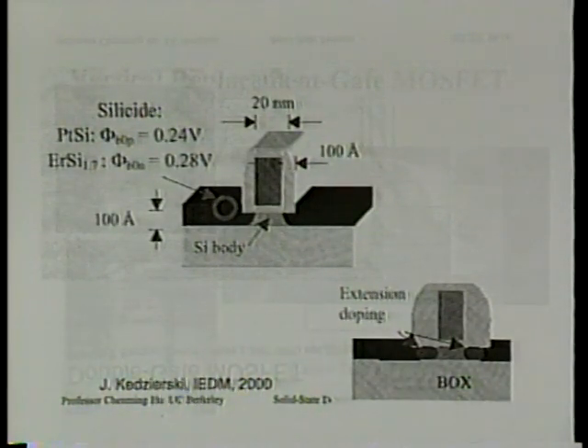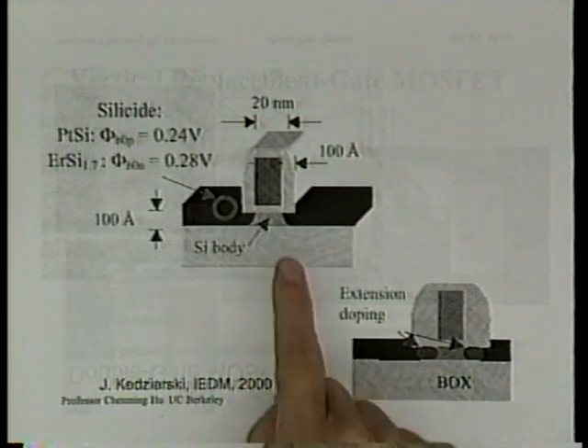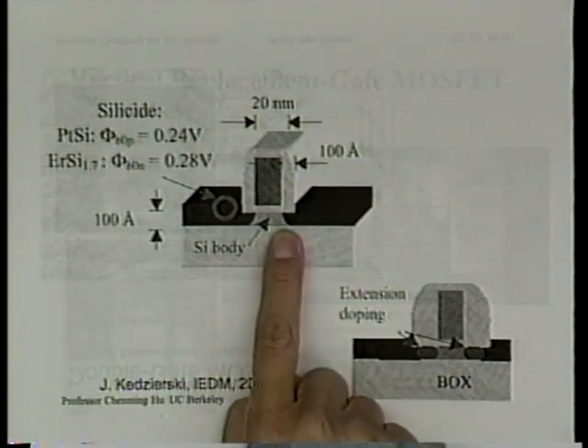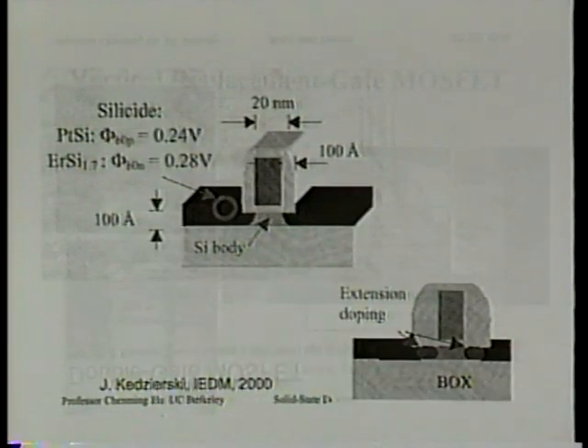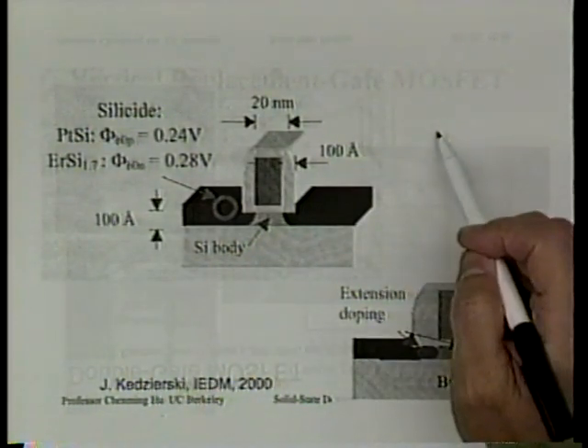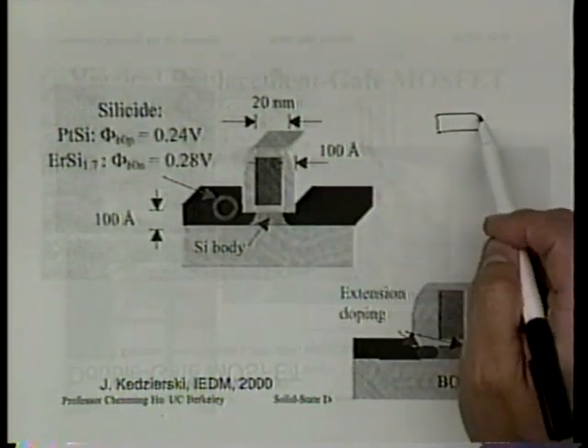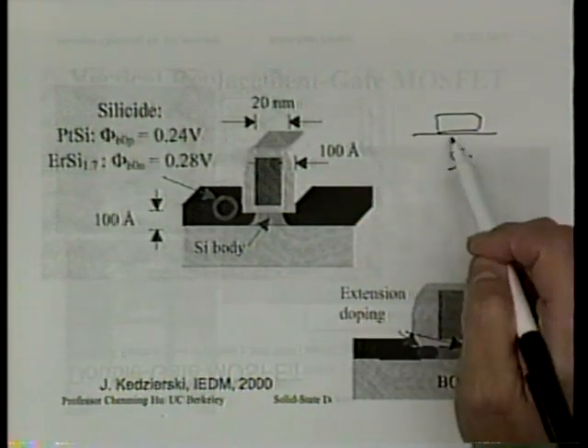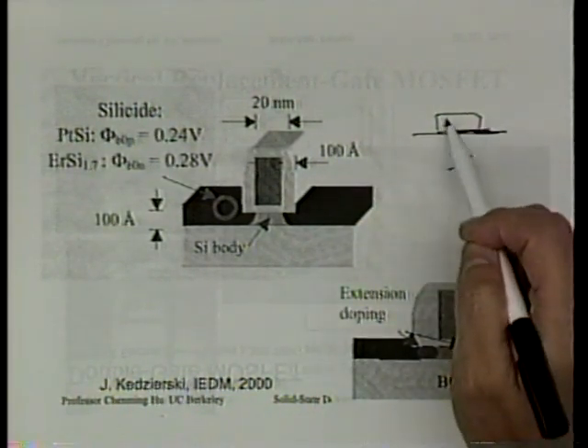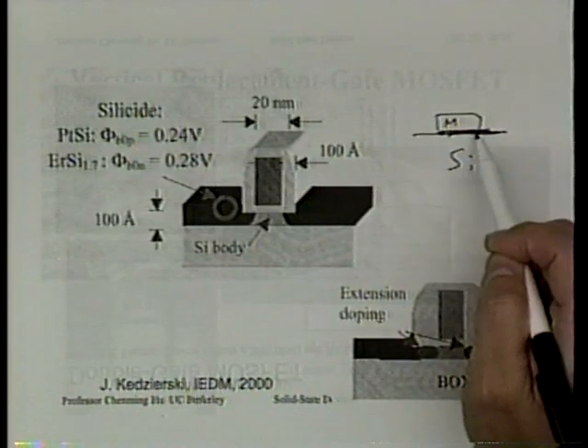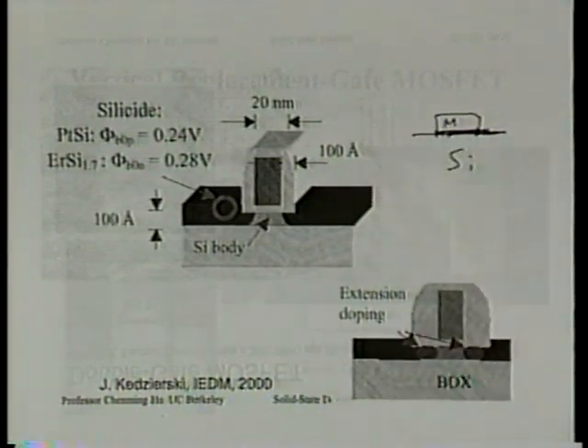Which means the interface resistivity better be very small. Now, this may not be something that you have considered seriously, but anytime you put silicide or metal on silicon, if this is silicon, this is either metal or silicide, there's a finite resistance due to the presence of the interface. As current flows through the interface, there will be some voltage drop, and that's called interface resistance.